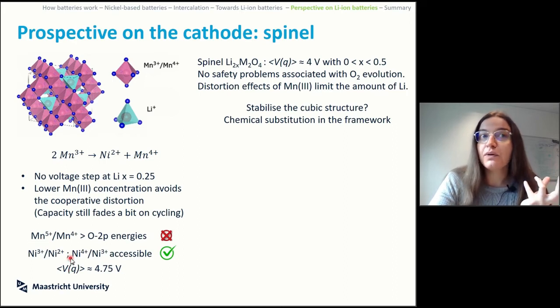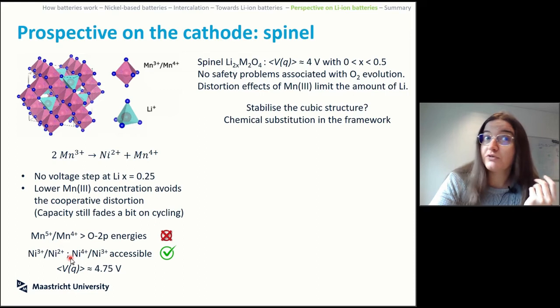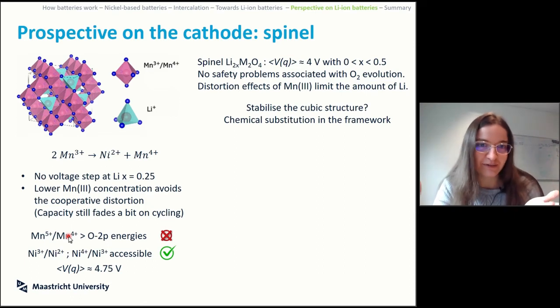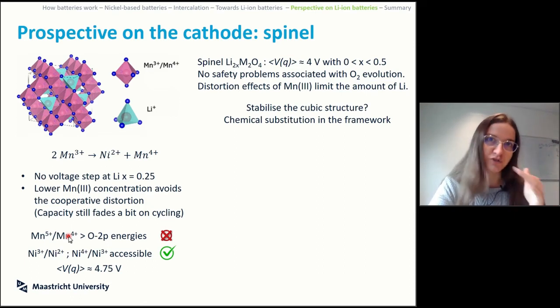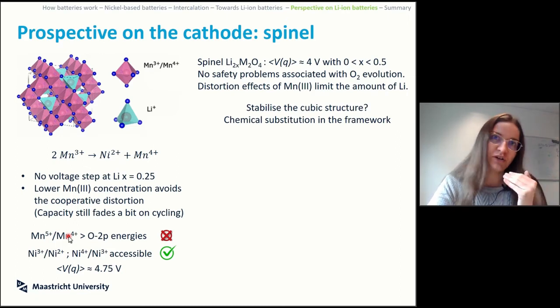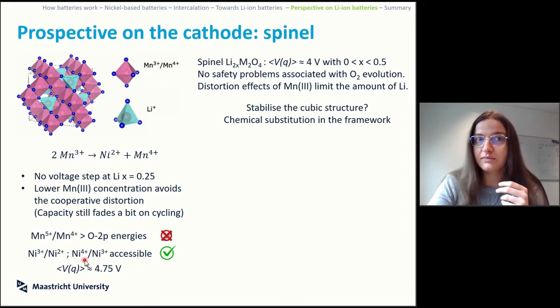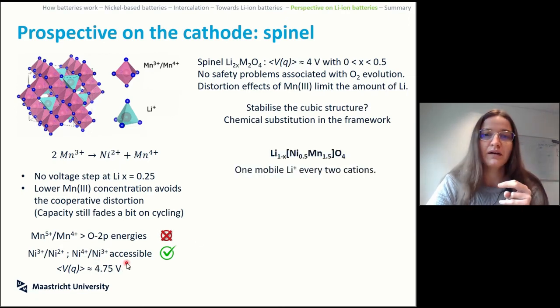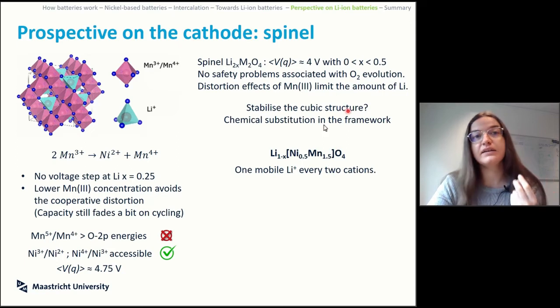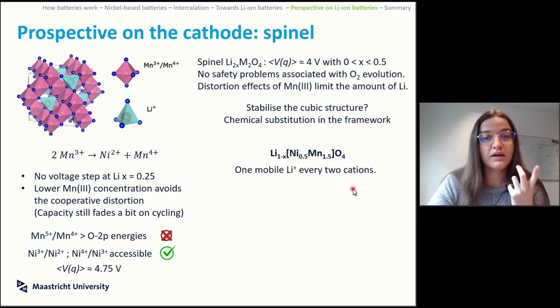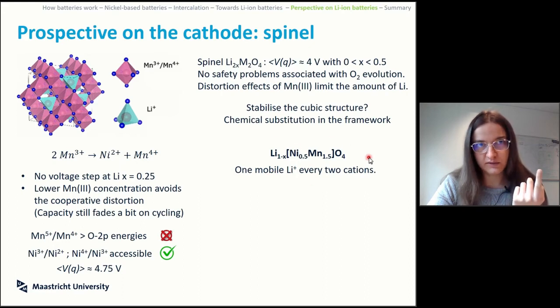What couples can you possibly use as redox couples? You need to remember you cannot go 5, 4, because manganese 5 and 4 have the oxidation states available, but they overlap with the oxygen 2p energy, so you will be doing electrochemistry on oxygen, not our scope. The nickel 3, nickel 2, nickel 4, nickel 3 couples are accessible, and if you manage to do this trick, then you can have a battery that works at 4.75 volt, so not even bad. So if you have this composition, half nickel and the rest manganese, there is one mobile lithium every 2 cations.